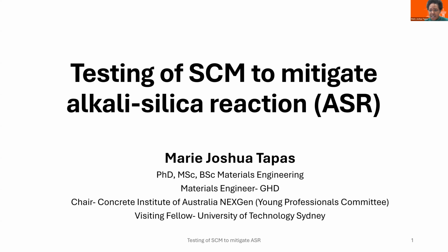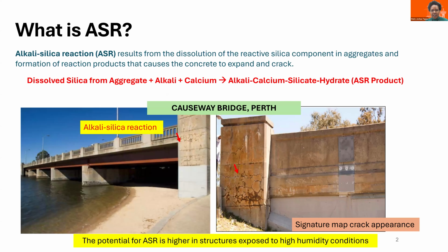Before I go to testing of SCMs, I'll give a short overview of alkali silica reaction. This bridge is a very good example of a structure suffering from alkali silica reaction. You can see here the signature map crack appearance because of ASR. ASR happens, for those who are not very familiar, when you've used a reactive aggregate in the concrete mix. Reactive aggregate means it has an unstable form of silica that has a tendency to dissolve under the high alkali pore solutions of the concrete.